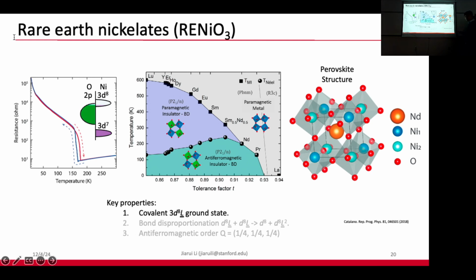Is that equivalent to oxygen deficiency? Not really. The oxygen is stoichiometrically 3, but it's just grabbing electrons, going from the oxygen band to the nickel. So it's a negative charge transfer system, to put it this way.